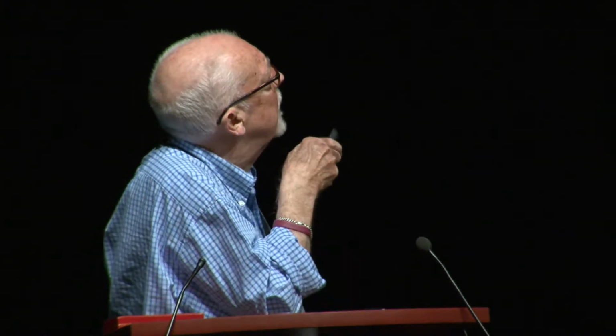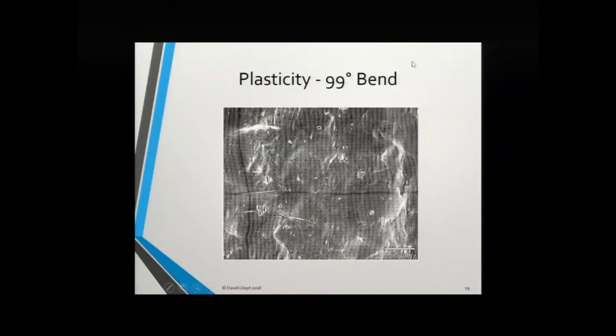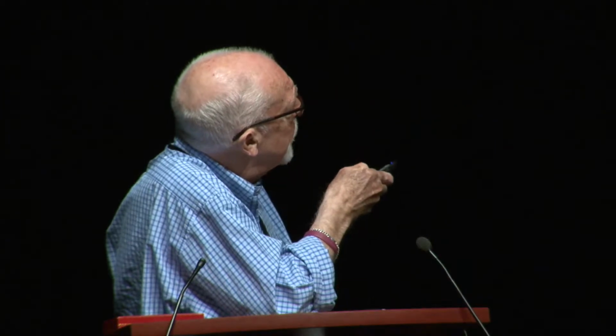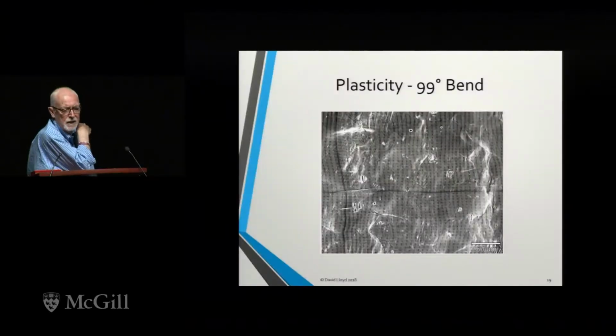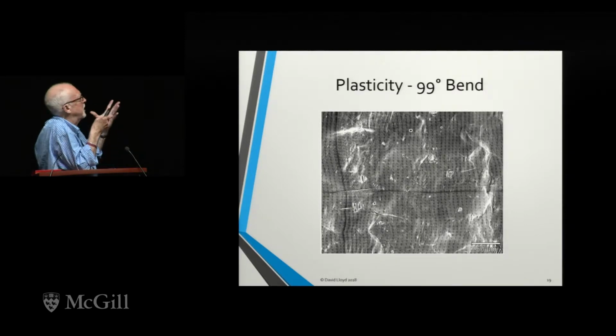This shows the 99-degree, same bend angle, but at a rather higher magnification. And here are our grain boundaries with a displacement. And these are intermetallic particles on the surface that at this bend angle have cracked. Now, the interesting thing about this technique is that you can monitor the development of strain around those intermetallic particles as the bending continues and as the damage continues.